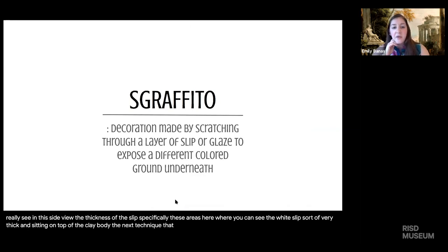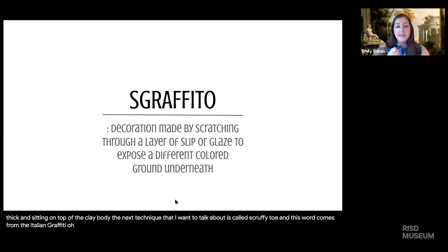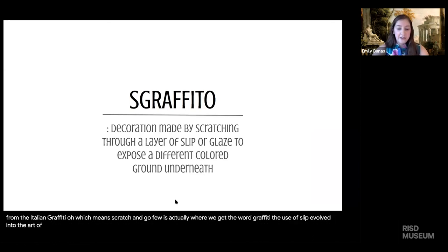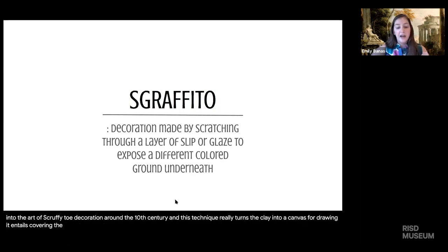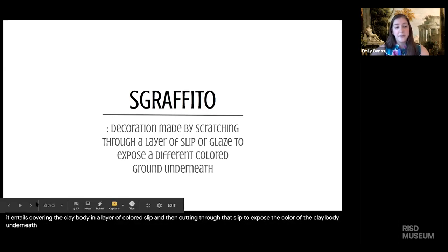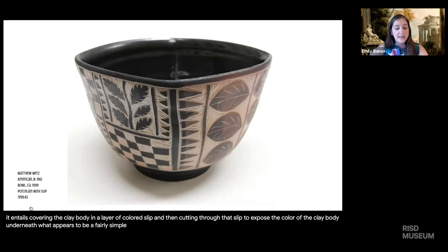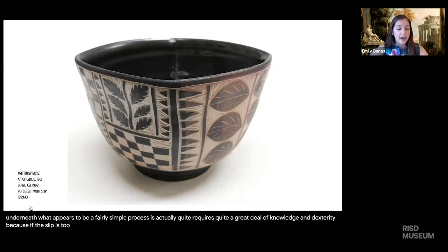The next technique is called Sgraffito. This word comes from the Italian "graffio," which means scratch — and graffio is actually where we get the word graffiti. The use of slip evolved into the art of Sgraffito decoration around the 10th century, and this technique really turns the clay into a canvas for drawing. It entails covering the clay body in a layer of colored slip and then cutting through that slip to expose the color of the clay body underneath. What appears to be a fairly simple process actually requires a great deal of knowledge and dexterity, because if the slip is too dry it will start flaking off, and if it's too wet your lines will be smudged.